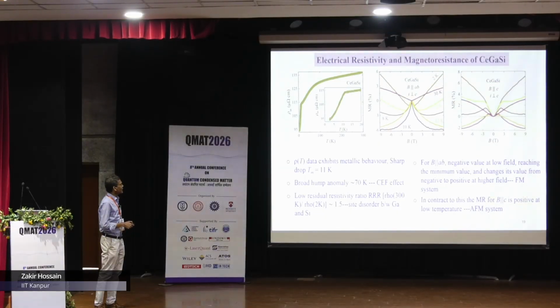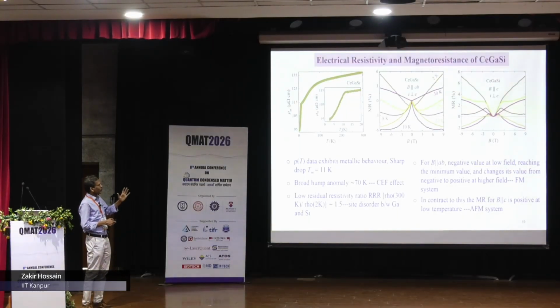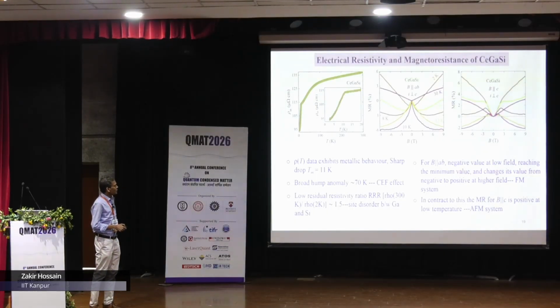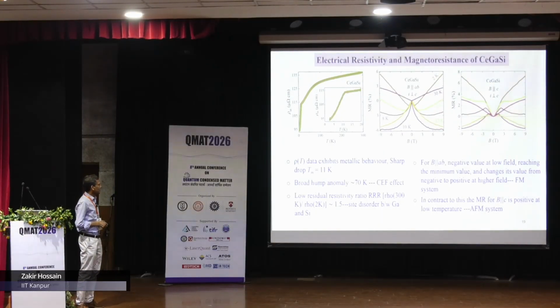So the 2 Kelvin data, if you see, there is a decrease. This is 30 Kelvin, and then this one comes like this, so there is some kind of a crossover from negative to positive at 2 Kelvin. And this one, if you see the B parallel C, also there is an increase and then decrease. Initially there is a positive, and then at higher field it becomes negative. So there is a change from positive to negative.